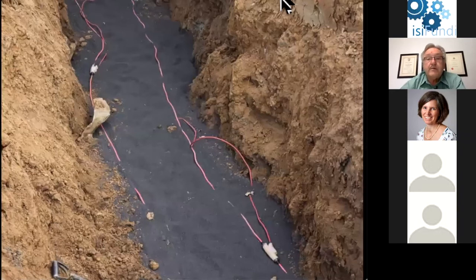These anodes then are located in the ground, some distance away from the pipeline. This photograph is of an impressed current ground bed where the anodes have been embedded in a conductive coke breeze backfill in order to improve their electrical contact with the ground. And these cables that you can see, this is a positive ring main, and each of the anodes is connected through an individual cable that is spliced into that ring main.